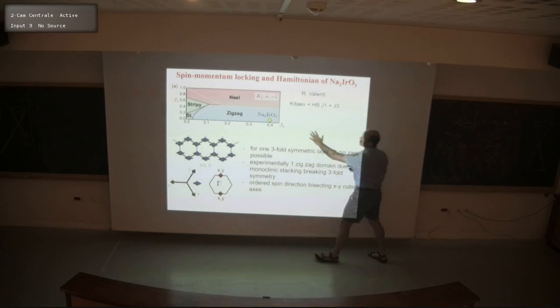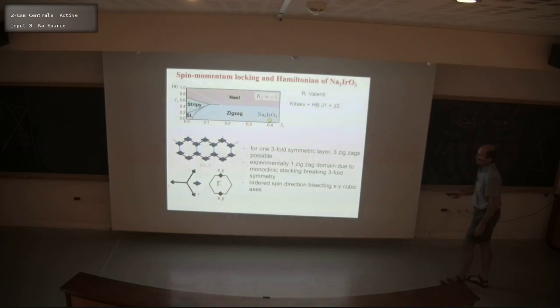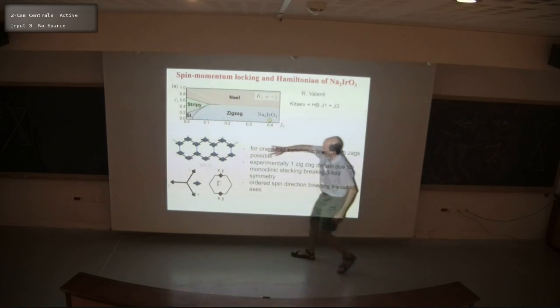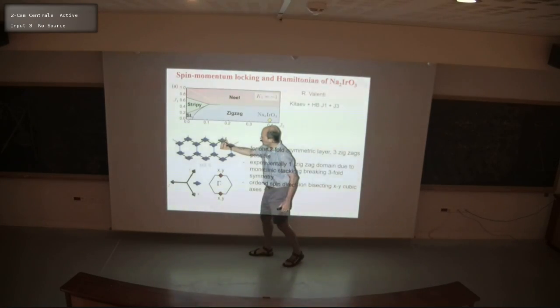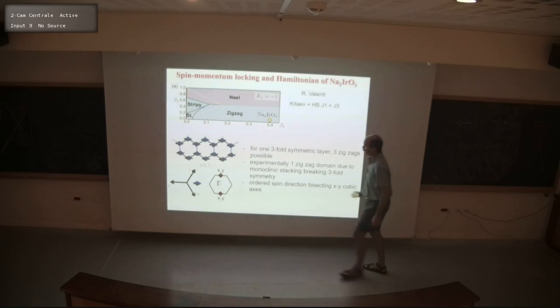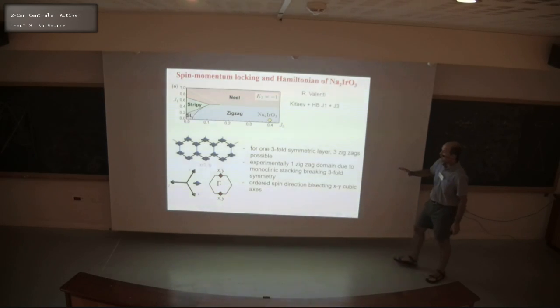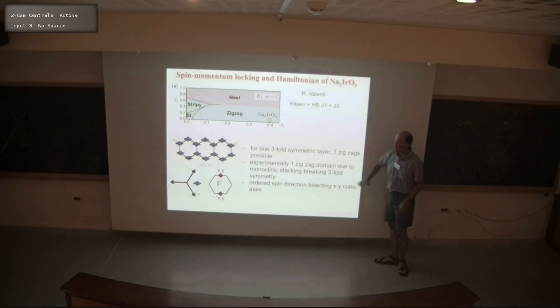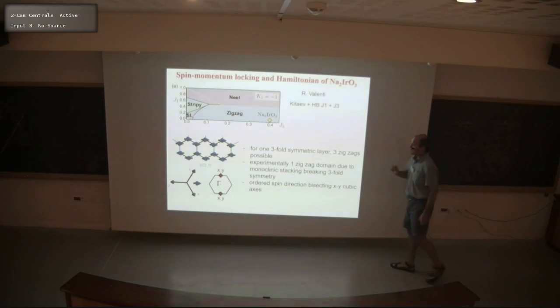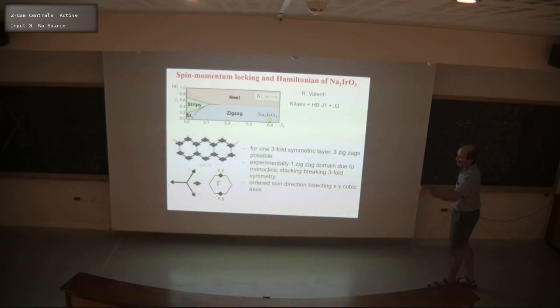Because this is a very large phase space. So in principle, if we just had a single layer, then one expects to find 3 zigzags. One that has the propagation vector vertically, and then the other 2 rotated 120 degrees. Now, experimentally, it's observed that there's a single zigzag in a single crystal with a monoclinic structure. And that's because this threefold symmetry is broken by the monoclinic stacking of the layers.